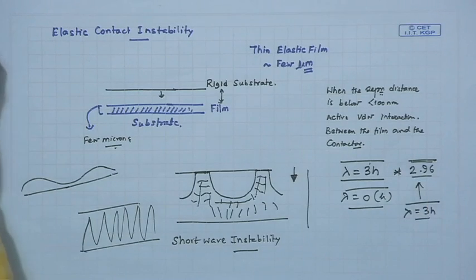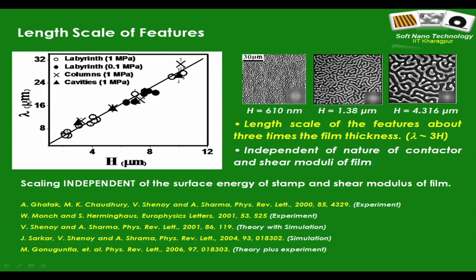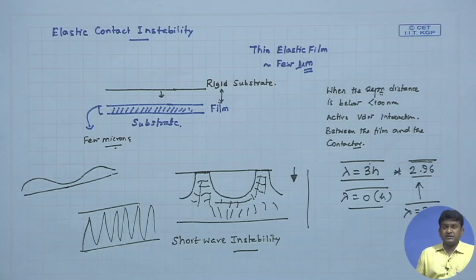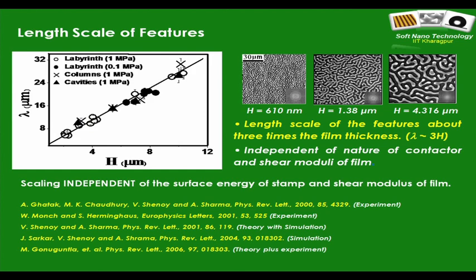So this is exactly what is shown in this particular plot. If you plot lambda versus h on a linear scale, you get a slope equal to 3. In fact, if you look at the symbols, something very interesting is there, and that is that this scaling relation is valid for all the morphologies. So you have cavities, columns, labyrinths, and more importantly, it is independent of the exact elastic modulus of the film. So you need to have a fully elastic film, but whether you have added 5% crosslinker or 10% crosslinker or 15% crosslinker, the scaling relations do not change.